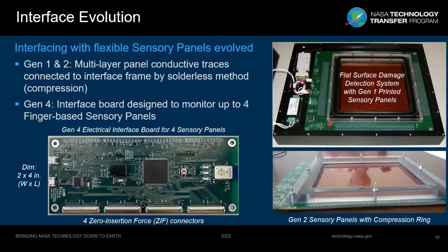Now, this particular ring on the interior diameter is about 6 by 6 inches. And we also used a rubber gasket between the interface, and we compressed the interface to hold it. Now, during the assembly of those panels, we also needed to use a jig to make sure that we had good alignment, so that those pads would align to the mating pads on the circuit board. Now, we changed our design a little bit, looking at a different direction, and that leads us to our 4th generation.